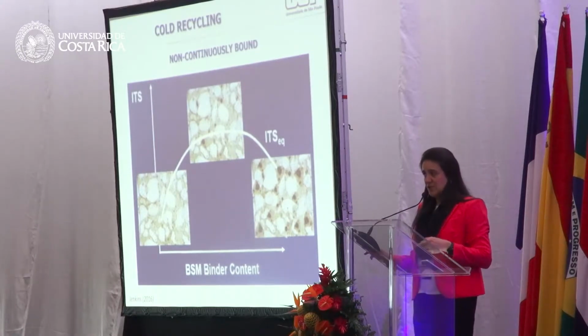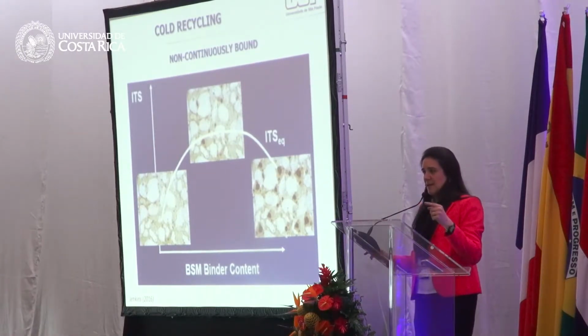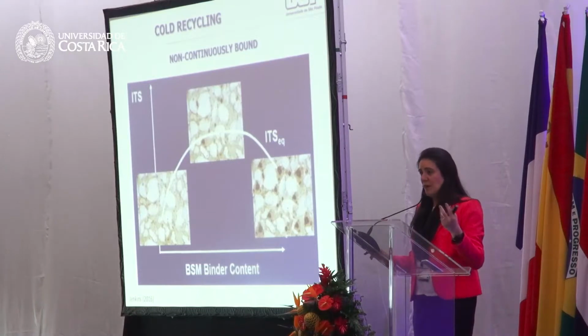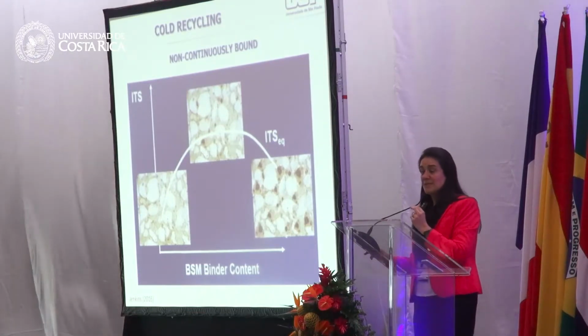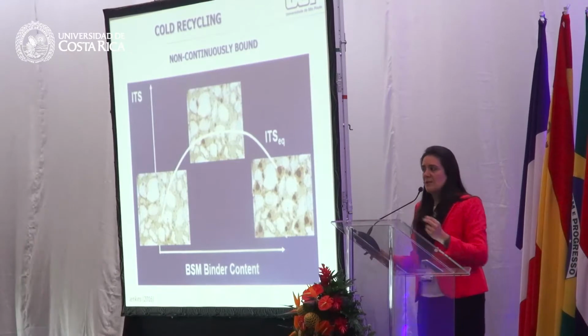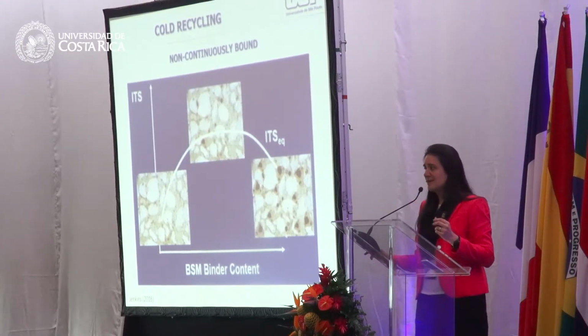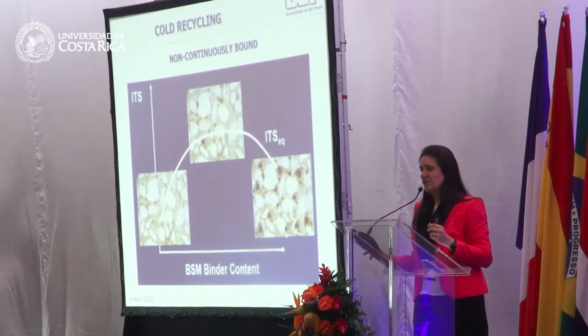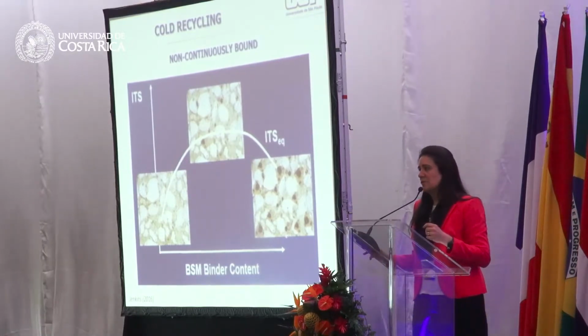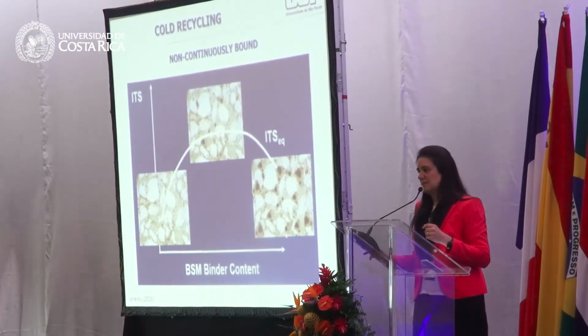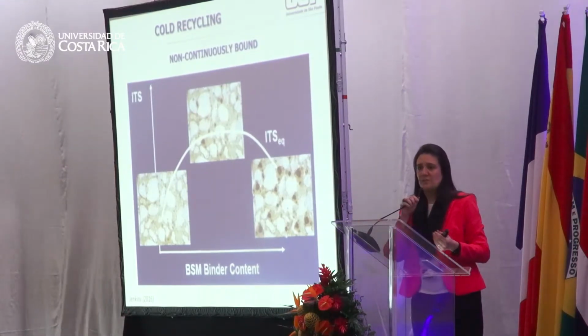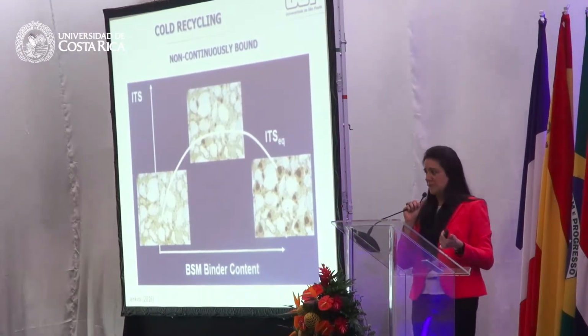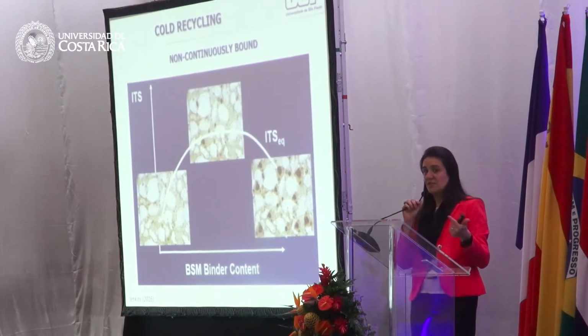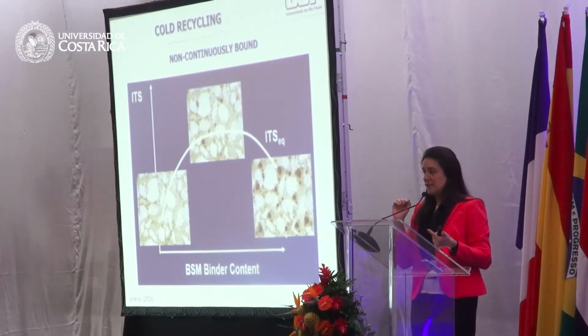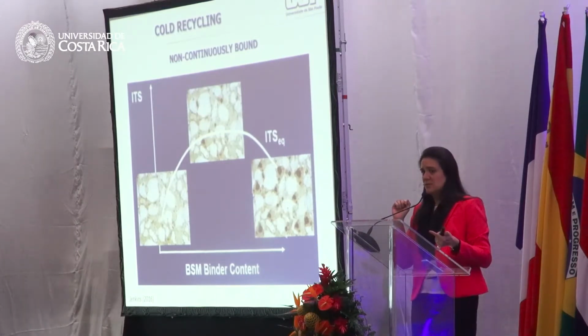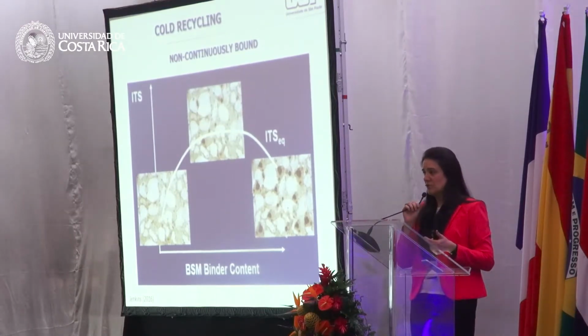This is just an illustration of what we used to call the optimum amount of binder. And this amount is not that much. We are talking about 2%, 2.5% maximum. I guess the project I've seen with the highest amount of asphalt binder was 3%. So it's supposed to be a cheap mixture. You are using RAP, so you do not have the transportation cost. You are not using that much asphalt binder, so it might be an interesting solution.